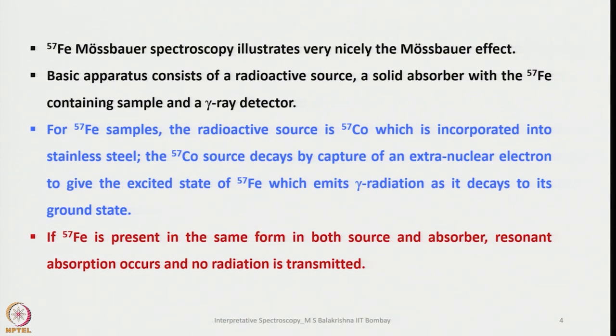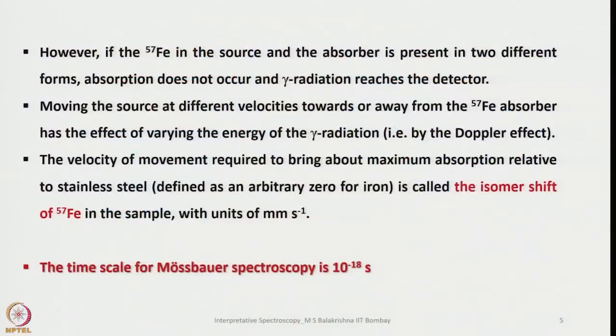If 57 Fe is present in the same form in both the source and absorber, resonant absorption occurs and no radiation is transmitted. So that's the reason we generate excited state 57 Fe from 57 cobalt through decay by capture of an extranuclear electron. However, if the 57 Fe in the source and the absorber is present in two different forms, absorption does not occur and gamma radiation reaches the detector. Moving the source at different velocities towards or away from the absorber has the effect of varying the energy of the gamma radiation. That we call the Doppler effect.